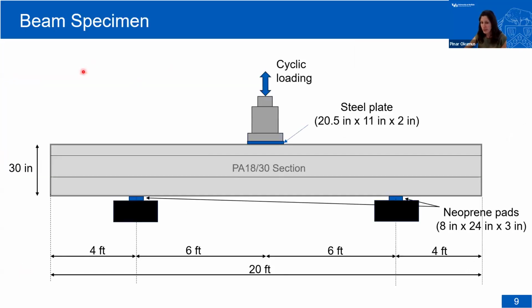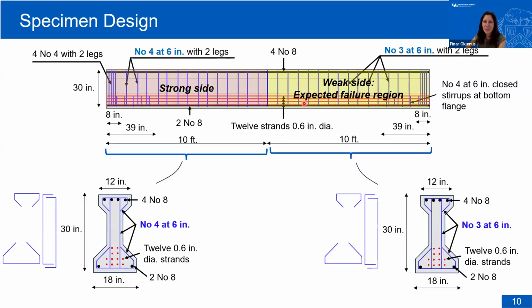So this was our beam specimen. We tested a 30-inch deep Pennsylvania standard section. If you're not familiar with it, that's similar to an AASHTO type I section beam. It's 20 foot long. We have a 4 foot overhang on each side because we did not want the transfer length to interfere with our results. And like I said, we're doing cyclic loading.